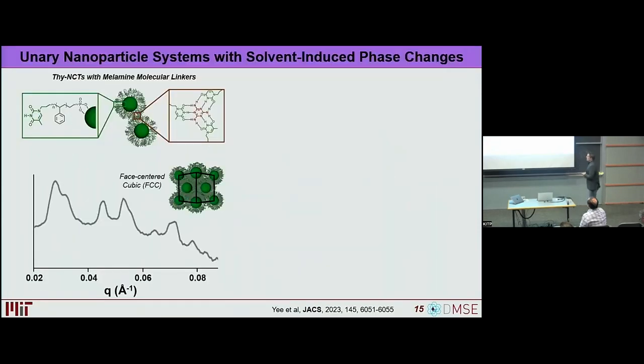So one of the things we've been focusing on recently is trying to make different types of symmetries, as we've shown with other types of nanoparticle assemblies. One thing that we've hit on recently is the ability to make these FCC-type lattices. We do so by using those thymine-terminated particles that we worked with before, but instead of throwing in a diaminopyridine complementary pair, we're just going to throw in this small molecule melamine. Melamine forms this nice sort of hydrogen bonding system with the thymine, and so we basically have a unary system where every particle can bond to every particle, mediated by some small molecules that we throw in.